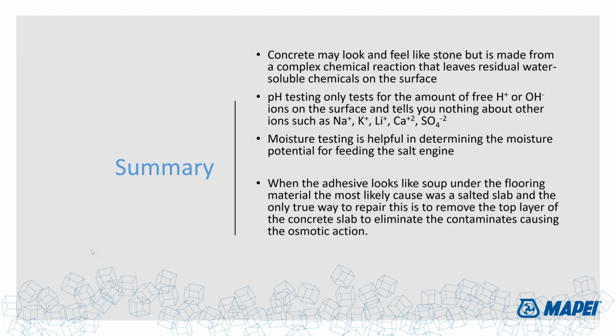Makes sense. All right. Another question. Will the water from taking a core sample reduce or skew the surface findings? No, because in a petrographic analysis you're not measuring water, you're measuring ionic composition, the amount of elemental presence, the amount of sodium elements, the amount of potassium elements. This test is, I wish I knew more about it, but it's very specific to the elements or ions that are left on the surface.